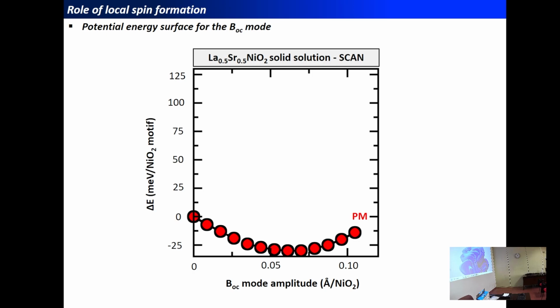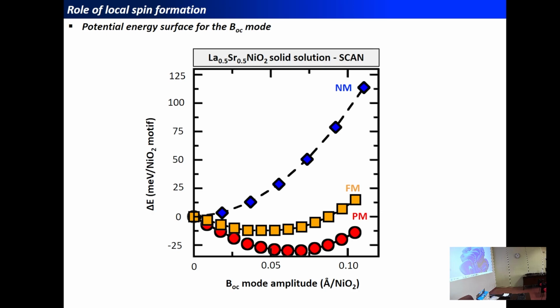You see that with the paramagnetic calculation, we can predict the existence of this distortion with the paramagnetic order in our simulation. If we repeat the calculation with a non-spin-polarized solution, you see that dramatically this type of simulation will never predict that these half-doped materials could exhibit, or should exhibit, a charge ordering. This type of disproportionation distortion will never appear. And this is in contrast to other calculations we can perform with simpler magnetic orders, such as the simplest spin-polarized solution, which is a ferromagnetic calculation, which also predicts that we should stabilize a breathing distortion, and so we should predict a charge disproportionation, and so a charge ordering in these half-doped materials.